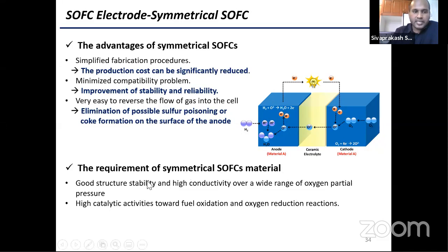The main requirement is good structural stability and high conductivity over a wide range of oxygen partial pressure. For example, when we use hydrogen in the anode compartment, the electrical conductivity decreases, but the same material in the cathode compartment shows higher electrical conductivity. So when we switch the fuel from compartment A to B, or anode to cathode, the cathode's electrical conductivity should be high enough to conduct electrons in the external circuit.